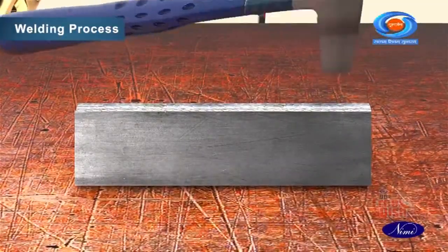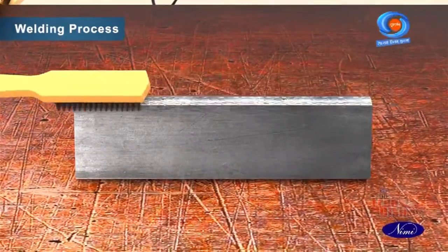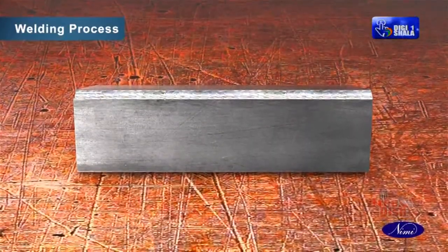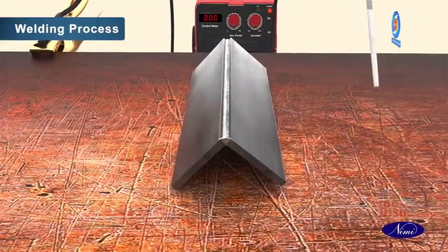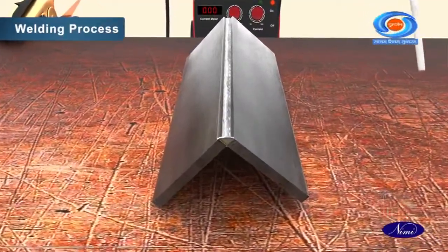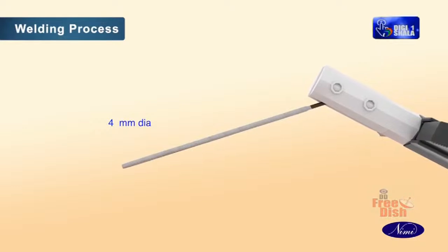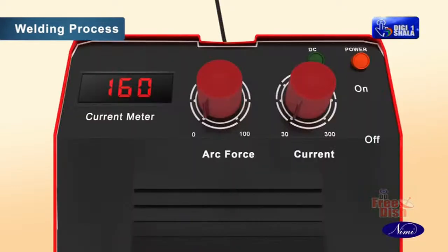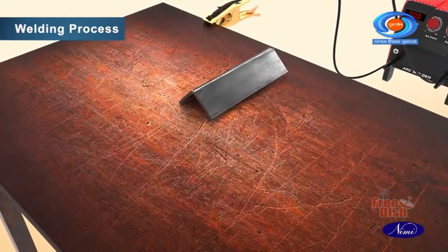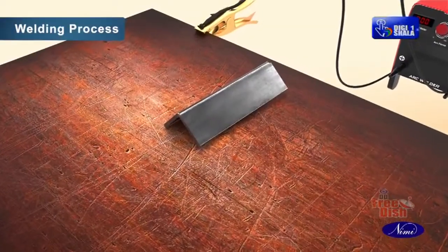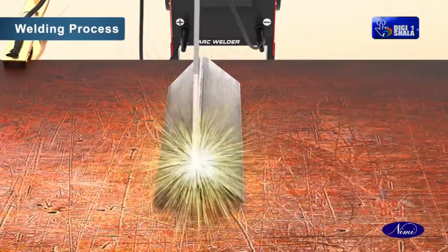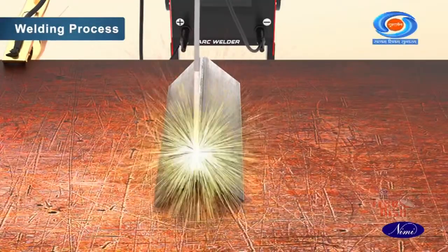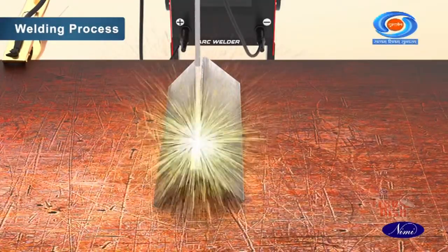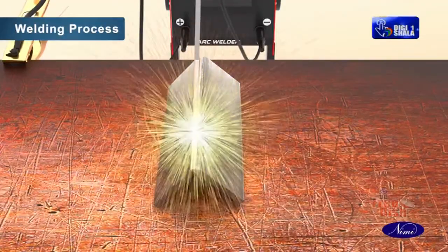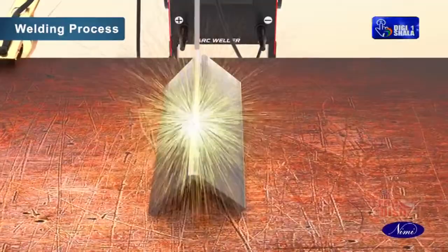Clean the slag from the first covering layer thoroughly. Ensure all the surface defects are rectified. Deposit second covering layer, that is the third run, using 4 mm MS electrode and 160 amps welding current. Use wider weaving motion to the sides of corner joint. A slower rate of travel than the first covering layer has to be followed. Use the same angle of electrode and arc length as used in first covering layer.